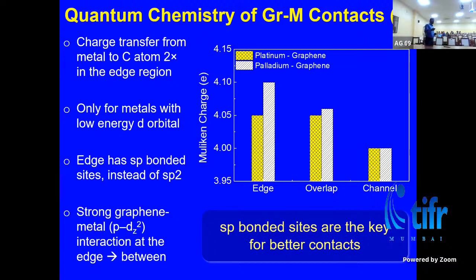Now the difference here is that this has a 3D orbital, a transition metal 3D orbital, which has an energy closer to the 2p orbital in the case of graphene, right? And that makes the difference. So that basically helps form this bonding channel. So you need a transition metal which has a 3D orbital, or in general an orbital state which is close to the 2p orbital energy level. Right. So we figured out that you need this kind of PD hybridization for this bonding channel to be formed. And if you can enable this PD hybridization in graphene, you can enable these bonding channels, which can improve the contact.